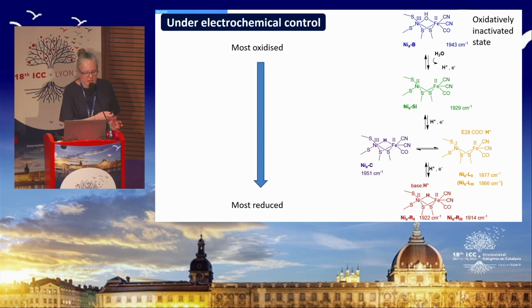And you'll notice here that while some of these states have a unique CO band position, at the nickel L redox level and the nickel R redox level, we've actually got a mixture of different substates, and we think that those differ in the position of the proton close to the active site, and that CO vibrational band is so sensitive to changes in electron density that it can sense a proton moving in the vicinity of the active site.